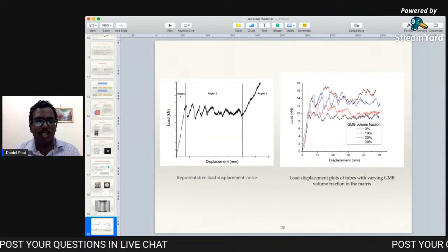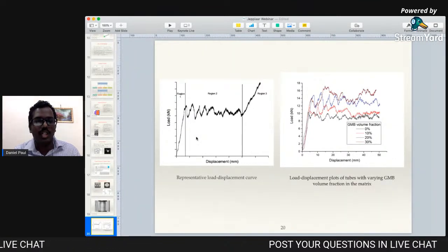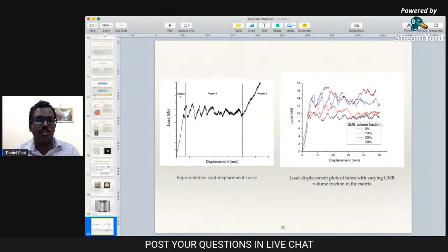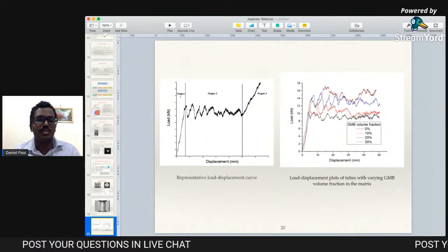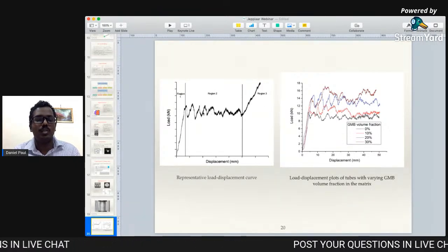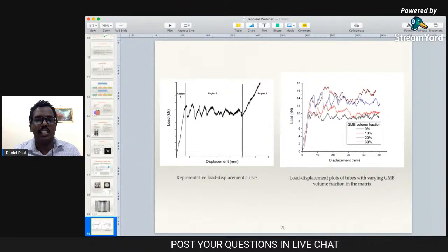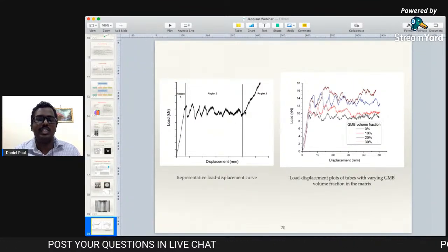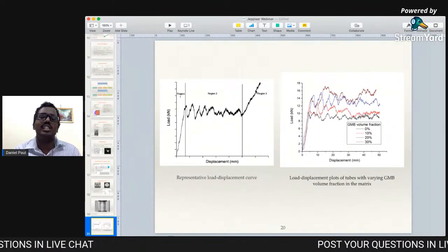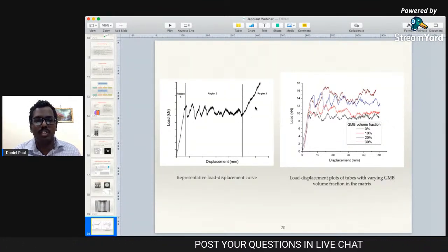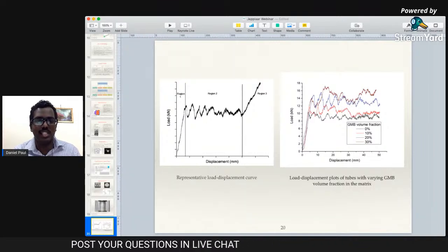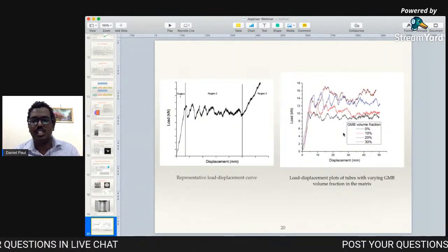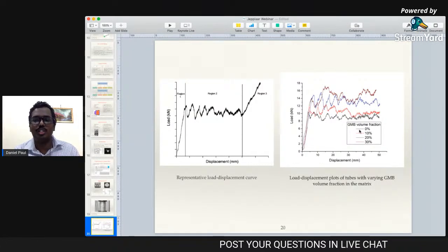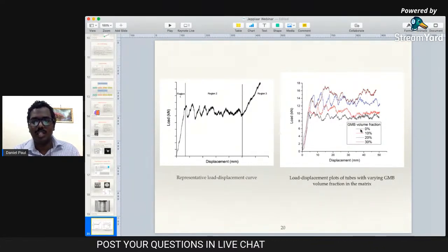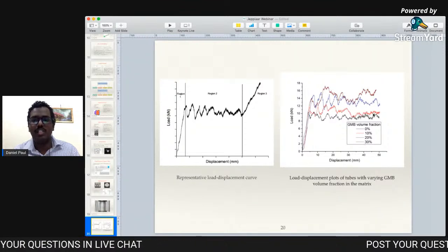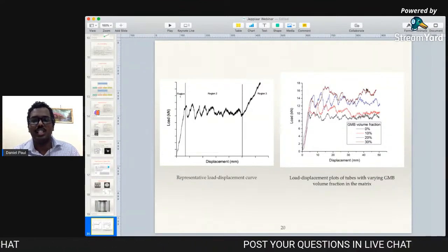So it's like a flat plateau region in which the load undulates at a mean load. The mean load is almost constant in this one. This mean load is called the mean crush load. And then after the entire tube has been crushed and it behaves again as a solid, the load again increases. We are not bothered about this third region. We are only bothered about the first region and the second region. As you can see, when we increase the amount of hollow particles within the matrix from 0% to 30%, we can see that the mean crush load is increasing at each level.